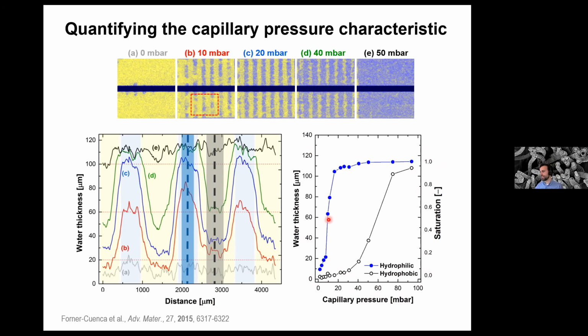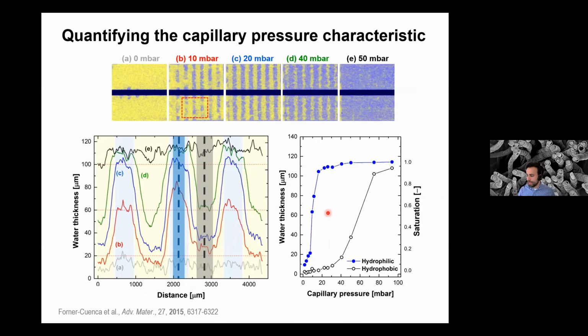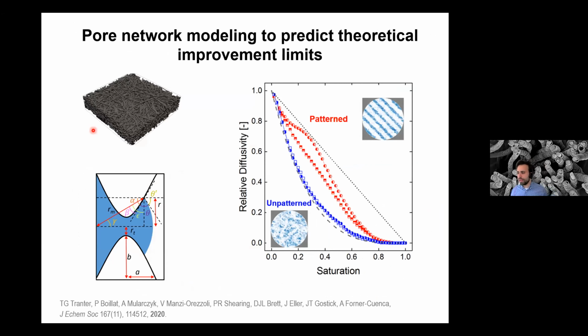And what you learn from these curves is essentially that at a very low capillary pressure, the water will fill the hydrophilic regions. And then at a much larger pressure, the water will fill also the hydrophobic region. So the space, the separation between these two lines will tell you something about the quality of this pattern, the segregation of this pattern. But the interesting thing is when you then take this material and you predict, so here we used pore network simulations, so three-dimensional simulations, to calculate the increase in effective diffusivity, because we do this work to decrease the tortuosity, and as a consequence to increase the effective diffusivity.